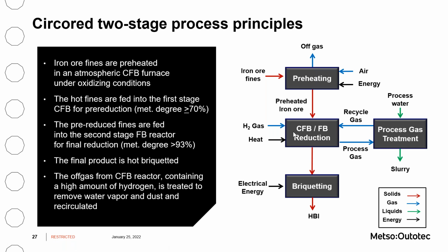Therefore, the fine ore material is fed into an atmospheric preheating stage. In case of magnetite as feed material, the material gets also oxidized to convert the dense mineral structure to a better reducible state. The hot ore is then fed at elevated temperature into the metallurgical core part, consisting of CFB and FB reactor. To create a closed loop system for the hydrogen, a process gas treatment sits aside, removing product water and dust. The metallized DRI gets downstream discharged to a briquetting section to produce HBI ready for shipping or smelter charging.